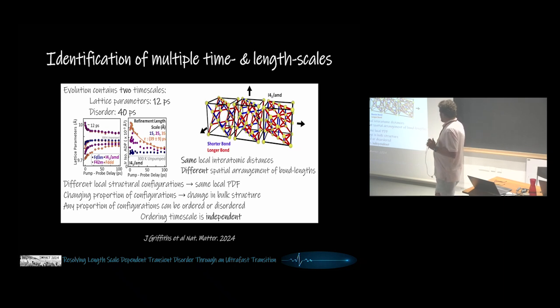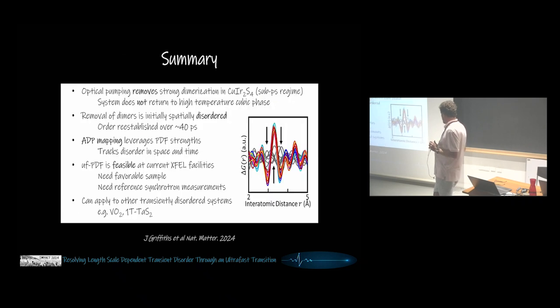But nothing actually limits disorder still being present in that and actually evolving over a longer time scale. That's exactly what we observe. So any proportion of configurations can be either ordered or disordered, which suggests that the ordering time scale is independent of the one that is suggested by the lattice parameters. Okay, so that's all I had to say.